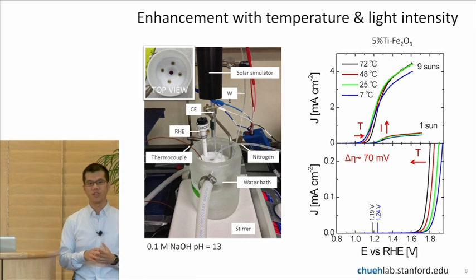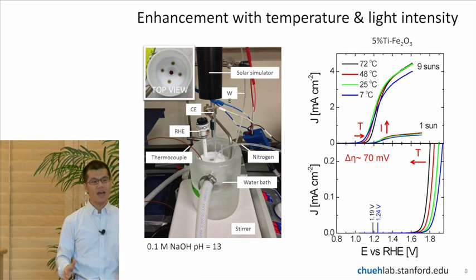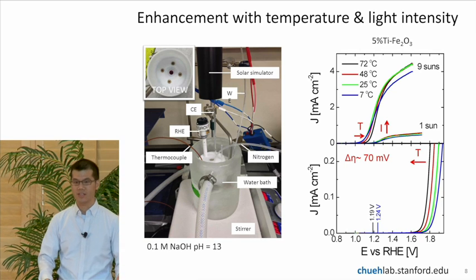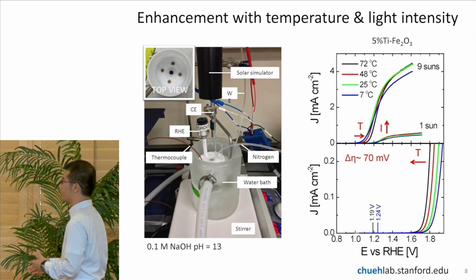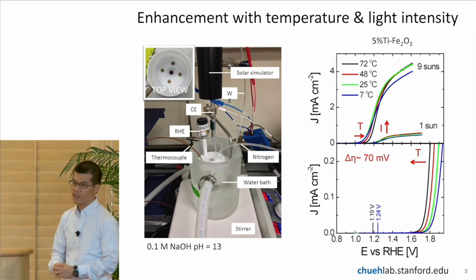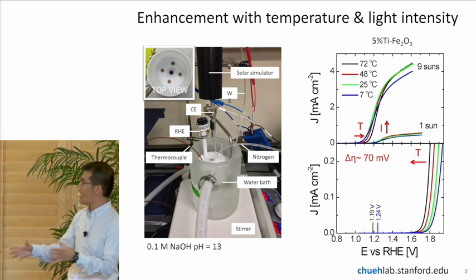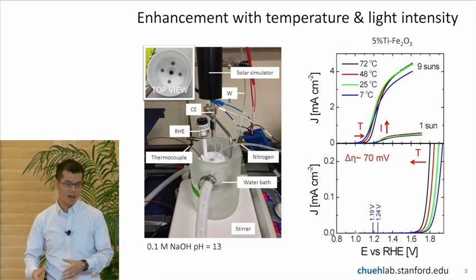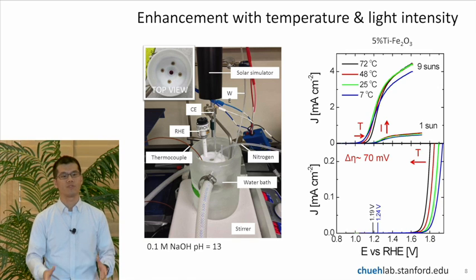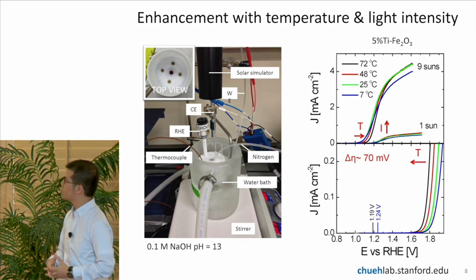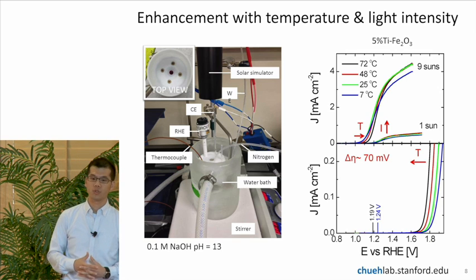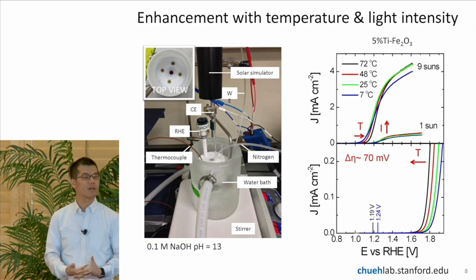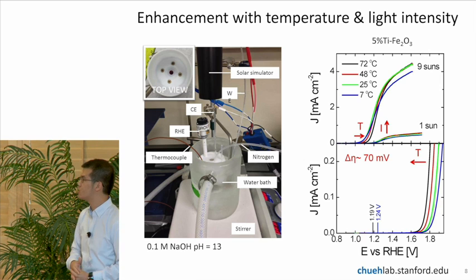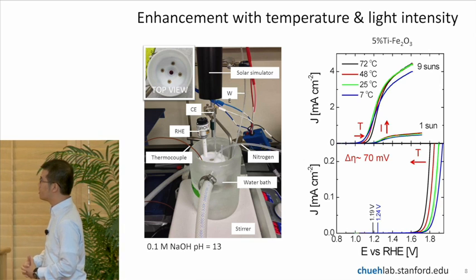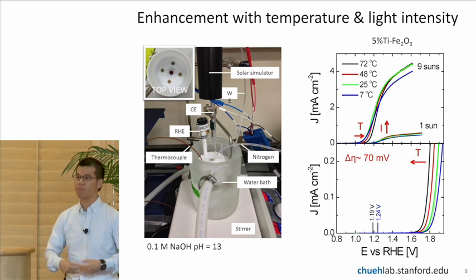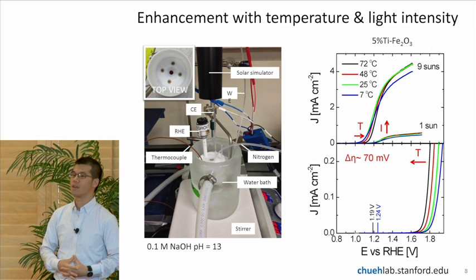And what we did next is we designed an apparatus not only to control the light incident on the cell, but also to control the temperature among various other things. So the setup on the left shows that we have a thermostatic controller, a water bath basically, to set the temperature of the cell. And we have a liquid electrolyte system that allows us to go close to 100 degrees Celsius. So this is a liquid-based system, so we're capped basically by the boiling point of water. So this is a standard electrochemical experiment, but we have very precise control of the temperature of the cell.